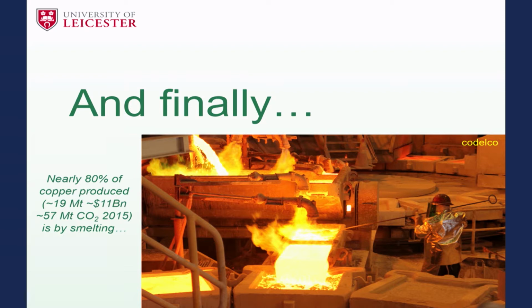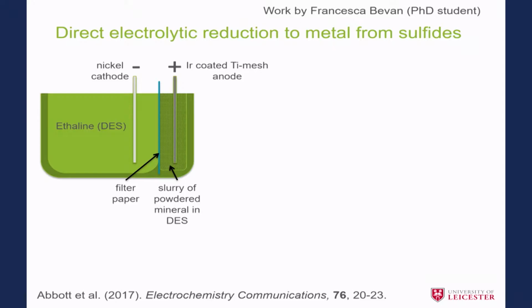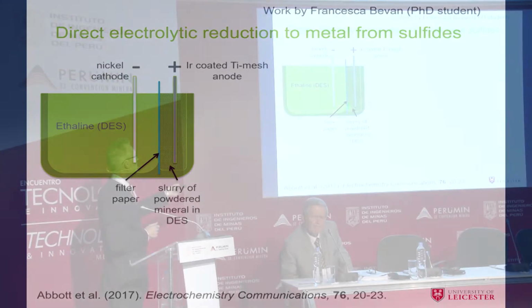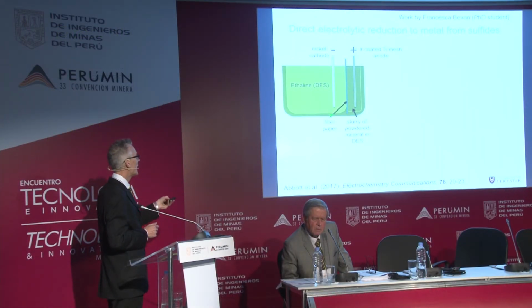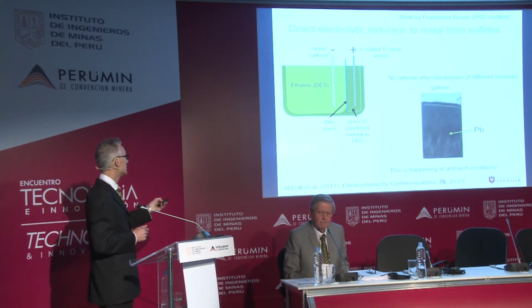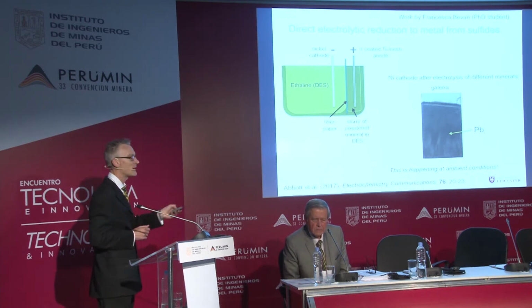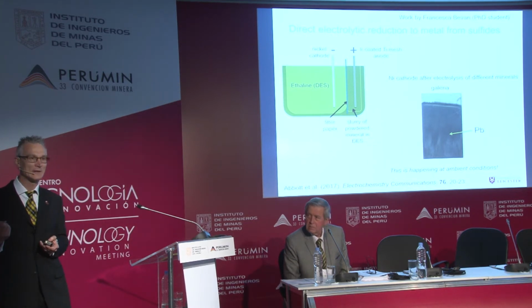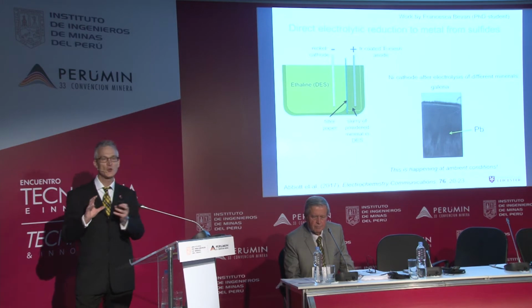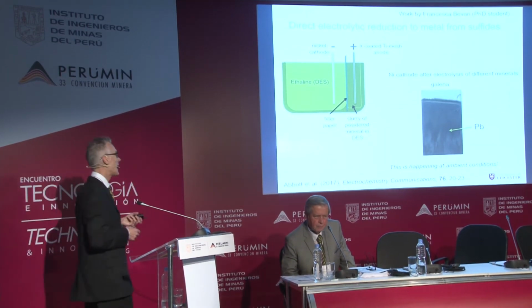Copper smelting. About 80% of copper produced around the world is produced through a smelter, a very high energy, high cost process. Now, what we've shown is we can put our powdered mineral against an anode in an electrolytic cell, separated by a permeable membrane from the cathode. We turn that on, and at the anode, the mineral is oxidized, and at the cathode, the metal ions are reduced. So for example, we can put galena in here, and on the cathode, we plate out lead metal. Now, this is what you do in a smelter. And smelting lead is a huge source of environmental contamination, but we can do it here at room temperature.